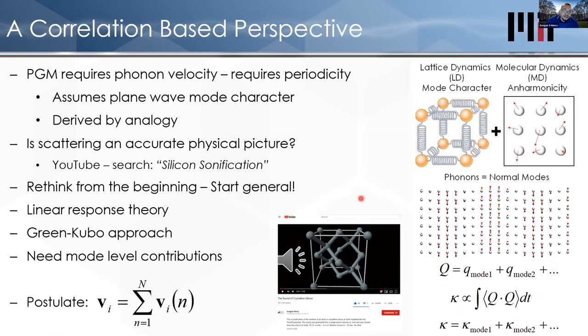So in essence, I'll skip the math, but in essence, that's what we did: we went back to the problem and restarted from the beginning. We got rid of this assumption of the modes being plane waves, and instead we rewrote the theory in terms of just the atoms themselves and their vibrations. We use a framework called lattice dynamics where we actually solve for the different normal modes, and we don't care what the normal modes look like. We then take those normal modes and we decompose what's called a molecular dynamics simulation, an actual simulation of the anharmonic, non-harmonic, non-linear motion of the atoms. We decompose it and use the normal modes as a basis set to do the decomposition. When we do it this way, we've essentially lost no information and we had to make no assumptions.